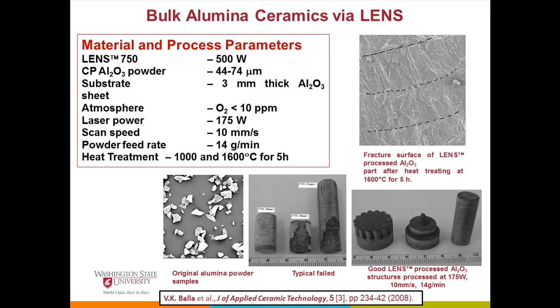This is another exciting work we did back in 2006-2007, with the paper coming out in 2008. We built a pure aluminum oxide part using LENS. Our feed powder was high purity aluminum oxide, standard commercial powder, in the 44 to 74 micron size range. We used an aluminum oxide substrate and low oxygen pressure, but the laser power was only 175 watts - really low end even for our system.